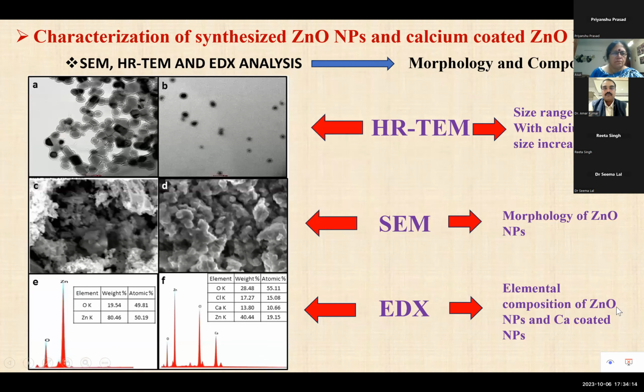Now, the morphology and composition were characterized through SEM, HRTEM, and EDX analysis. In one of the studies, the TEM showed that the size range of the nanoparticles synthesized was between 20 to 100 nanometer, and with calcium coating, this size increases. In morphology, we have seen clusters, from spherical zinc oxide nanoparticles to somewhat bean-shaped zinc oxide nanoparticles that we have synthesized. And EDX studies gave the elemental composition of zinc oxide.